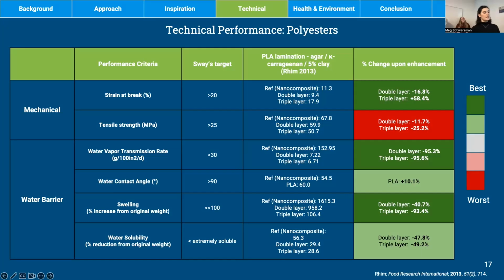So we see the greatest improvements for the triple layer film in the strain at break, the water vapor transmission rate, and for the swelling. And then there are also moderate improvements for the water contact angle and for the water solubility. But unfortunately, they did report a pretty large decrease in the tensile strength performance.